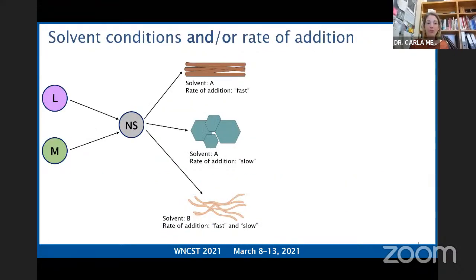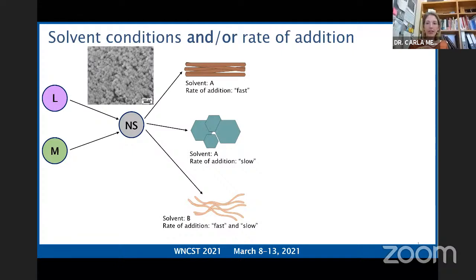We then moved on to a different MOF, or a different ligand and metal ion. And I do apologize, I'm intentionally vague here because these are quite new results that we're still working on and we're quite excited about. But in this case now, we have our ligand, we have our metal ion. And in all cases, when we mix our microemulsions together, regardless of the synthetic conditions, we always initially, after the addition of one to the other, start with the formation of nanospheres. It's probably a little bit hard to see on the screen there, but we have nanocrystals around 20 to 30 nanometers. After that, these nanospheres seem to develop into either needles, hexagons, or what we call noodles.